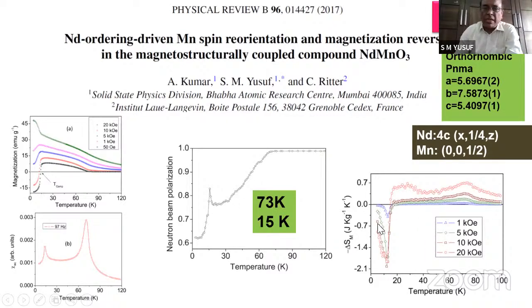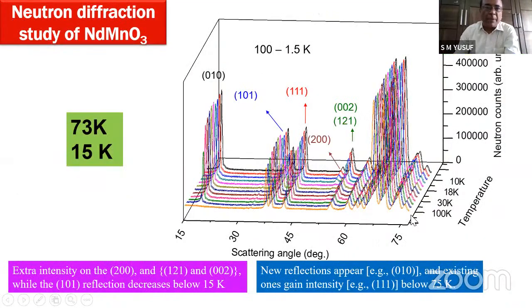When we calculated the magnetic entropy change, we see that across this compensation temperature there is a polarity reversal of minus delta SM, the magnetic entropy change. As you know, the positive part corresponds to magnetic cooling, whereas the negative part of minus delta SM corresponds to magnetic heating. So you get both magnetic cooling and heating out of the same system. We have done a detailed neutron diffraction experiment down to 1.5 Kelvin.